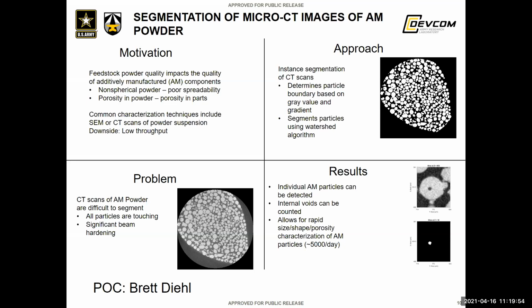And then he's trying to characterize the powder itself, as well as look at individual defects within the powder and characterize the defects in relation to the powder that they are within. And we're trying to have that for all of our powder sets, so that if we're seeing large amounts of, say, these gas defects, we're able to link it back to the powder.